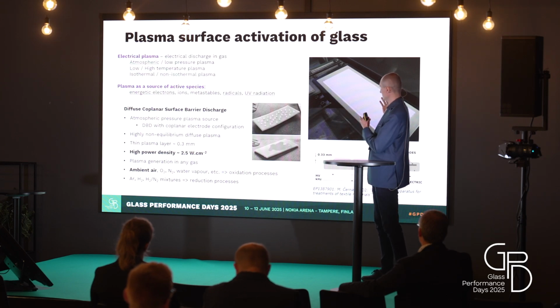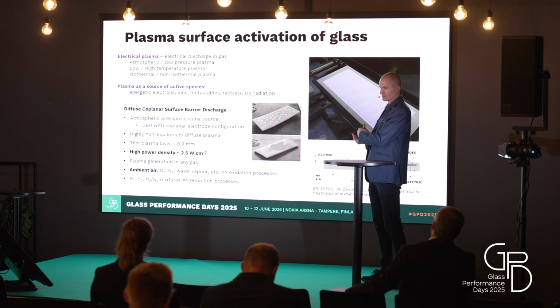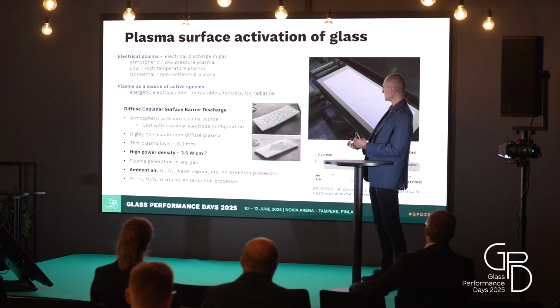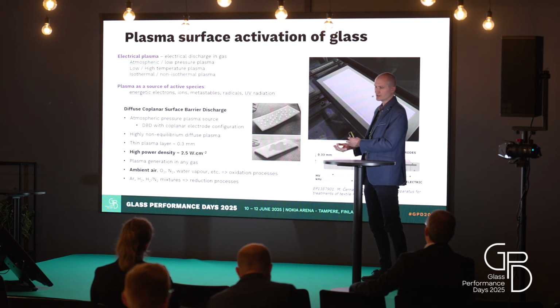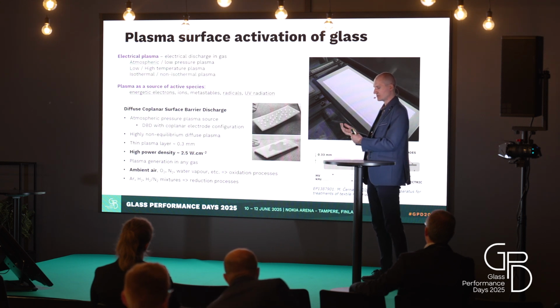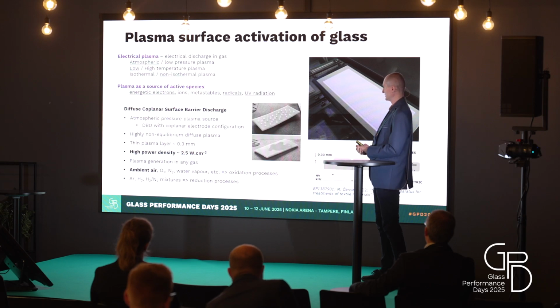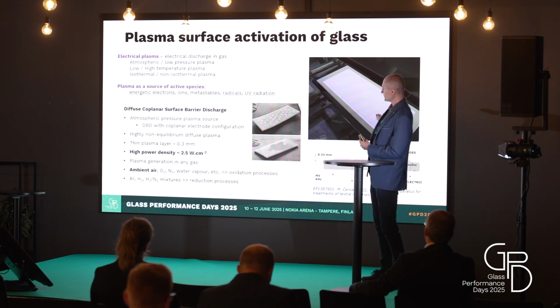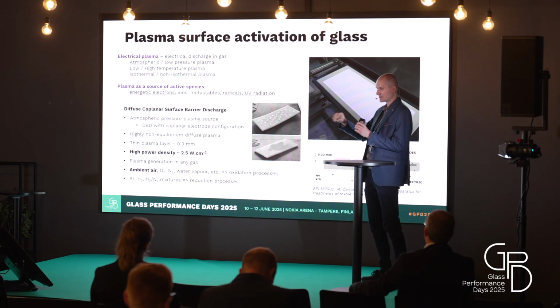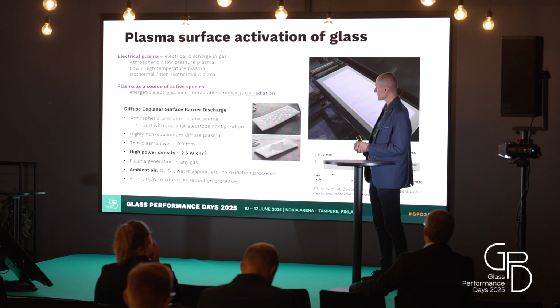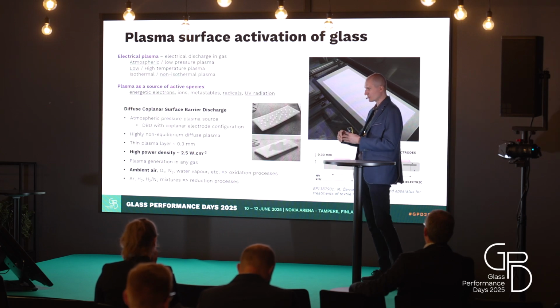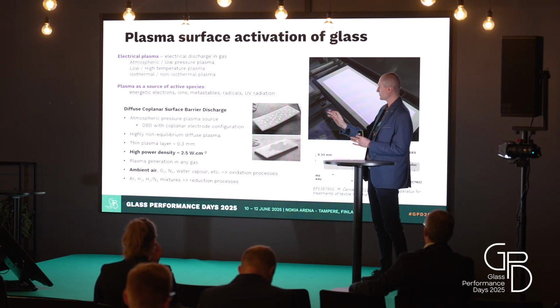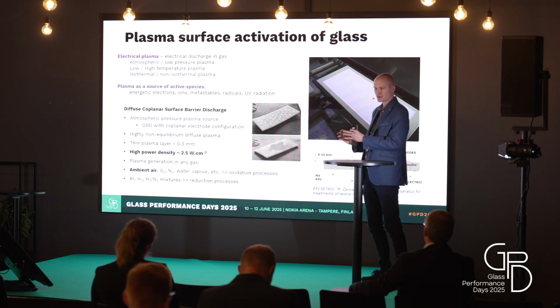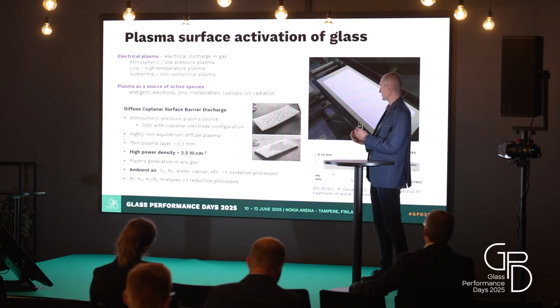Given by the geometry and the characteristics of the way we generate plasma, we can achieve very high power densities in our plasma system, which allow us to use very short plasma treatment times. With this configuration, the plasma is generated as a thin layer of the electrical discharge. Originally, this system was developed for a completely different application, for fabrics and this type of materials, but it turns out that there is a very nice effect also on glass.